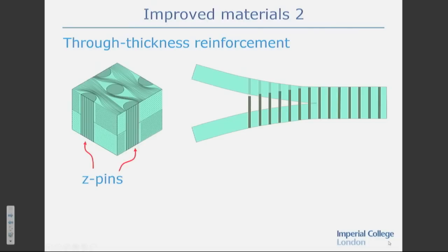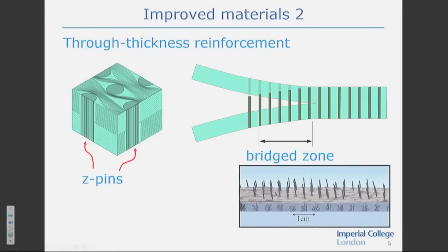How does it work? Well, imagine that fracture toughness test we did before. Well, this is a Z-pinned one, and they are designed so that these pins pull out as the crack's advancing. So the crack tip here, the separation tip advances, and in the wake of the tip, these pins are being pulled out, and in the process of pulling out, they're absorbing energy. And it's a bridge zone I've identified there where the energy absorption is taking place.